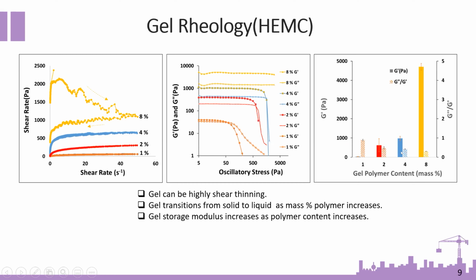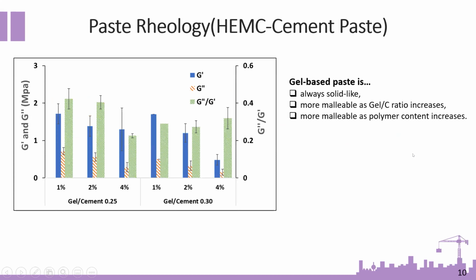We also plotted here the gel storage modulus versus the polymer content. As you can clearly see, as we increase the gel concentration, the gel storage modulus increased, whereas the ratio of the loss modulus to the storage modulus decreased. We also performed some paste rheological characterization.